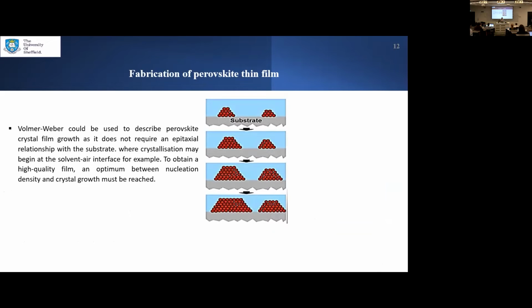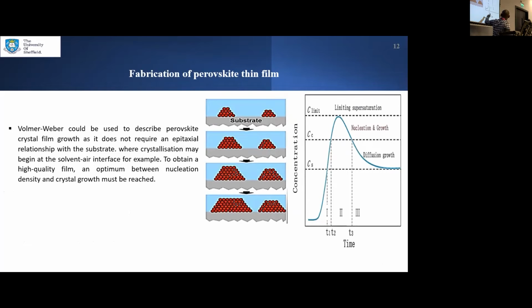How do these crystals form after you have spin coated your perovskite solution on a substrate? Basically, we tried to emulate the Volmer-Weber coating method, which shows how the perovskite transforms after a certain period of time. This is just how the crystallization moves from the initial stage, when the solution is coated on a substrate, the concentration tries to increase, and it reaches the maximum concentration, resulting in the formation of the perovskite crystal surface.